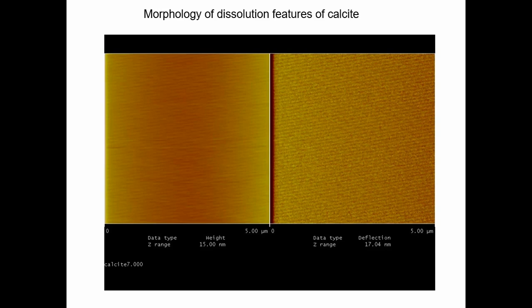As you've heard, my main research has been in atomic force microscopy. Here is a cleaved surface of calcite. I've done a lot of work with calcite. And here is a 5x5 image. Left-hand side is height, right-hand side is deflection. They're the same surface. We often use the deflection image because it looks nicer, but the height image gives us the information in the Z direction, and you can see the height here was set at 15 nanometers. So it's truly on a nanoscale in the Z direction.